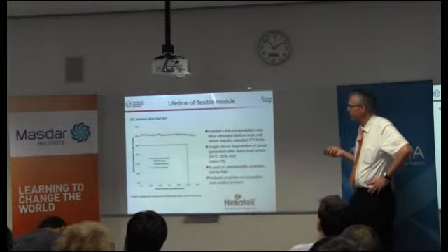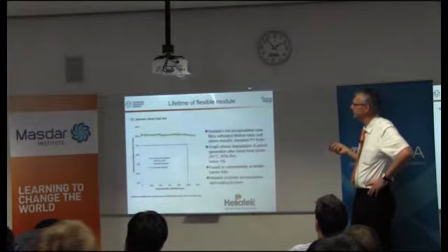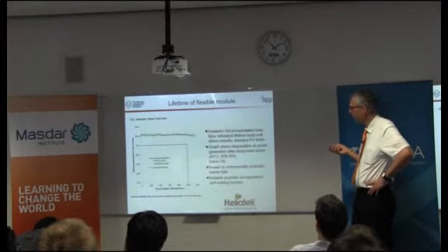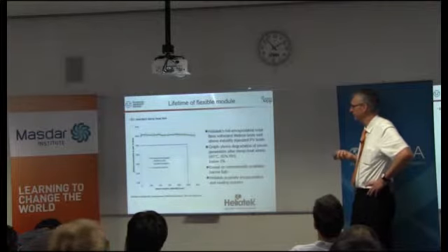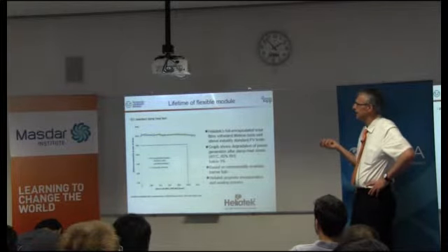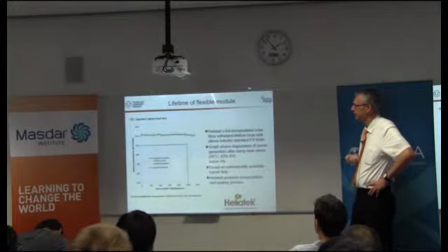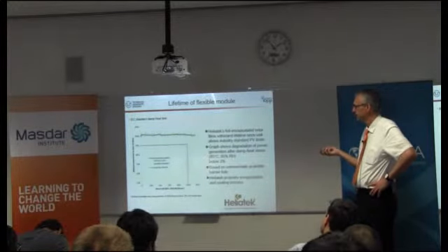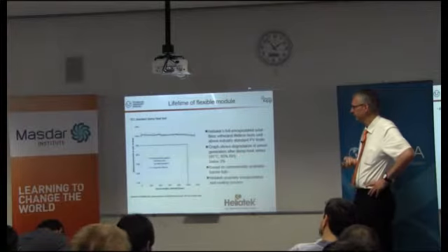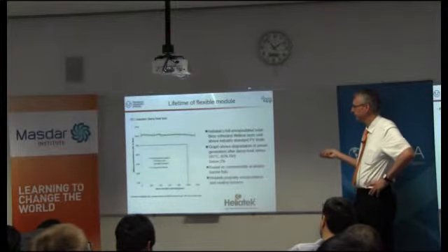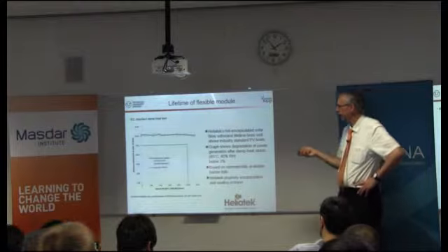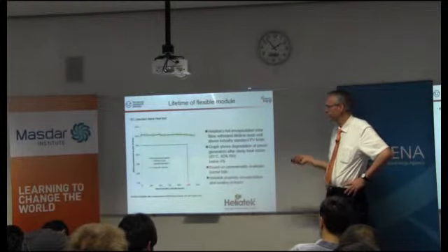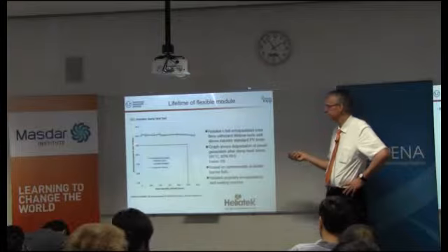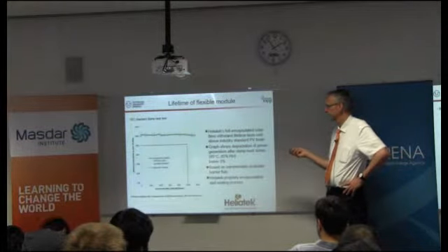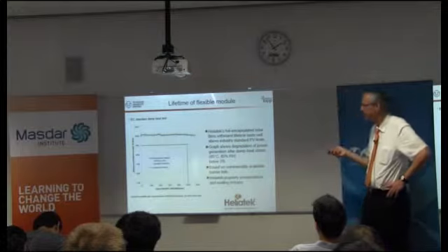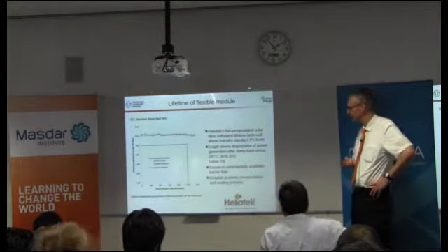These are data from Heliatek for a commercially relevant device. It's actually a foil encapsulated flexible module, and this is an IEC standard damp heat test, which is treating the modules at 85 degrees temperature, 85 relative humidity. And the standard requires that over 1,000 hours there should be only 10% decay, and the Heliatek module had a 3% decay. So it easily matches already these standard damp heat tests.